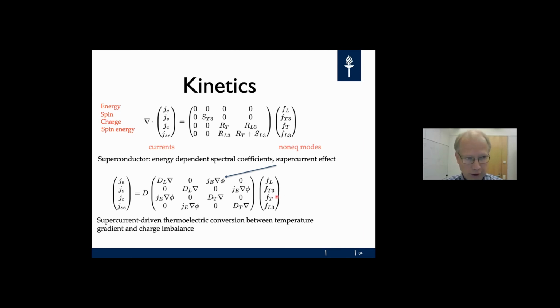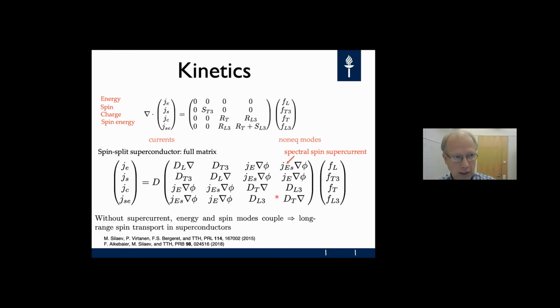Now, if you have a spin split superconductor, you can guess that this matrix fills up further, and you couple all the different modes. There should be a gradient here—apparently I'm missing some gradients, but yes. You get diffusion that couples the energy and spin modes, and charge and spin-energy modes together. Then you can also have a possibility of spectral spin supercurrent that couples the rest of the terms.